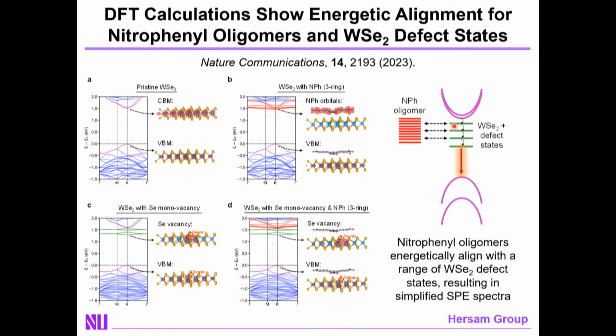And as a result, the only energy that remains is the lowest energy peak, which then shows strong single photon emission. So this is a case where we're now utilizing, again, the organic add layer as a means of passivating, or at least turning off the effect of the defect states, thereby giving you much more homogeneous and reliable single photon emission.